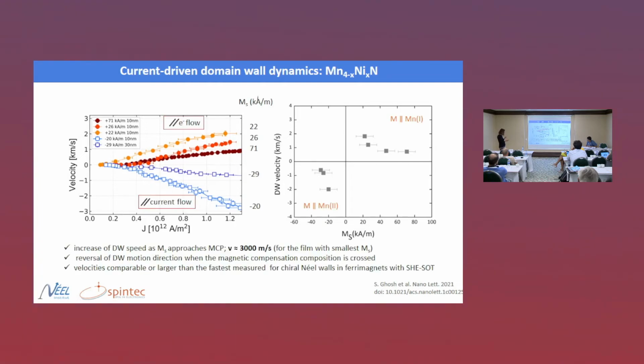So what are the main results of this study? The first one is that we have this huge domain wall velocity. We get to 3 kilometers per second, so 3000 meters per second close to this, which corresponds to about, I think, 0.18 of nickel doping. And the second result is the reversal of domain wall motion when we cross the magnetic compensation. To be noticed that if we take, for example, a system with platinum, gadolinium, cobalt, driven by spin-orbit torque, the domain wall does not change direction when we cross the compensation, because, as I say, it's the DMI sign and the spin Hall effect sign that is not expected to change across the compensation. So it is really typical of this system.